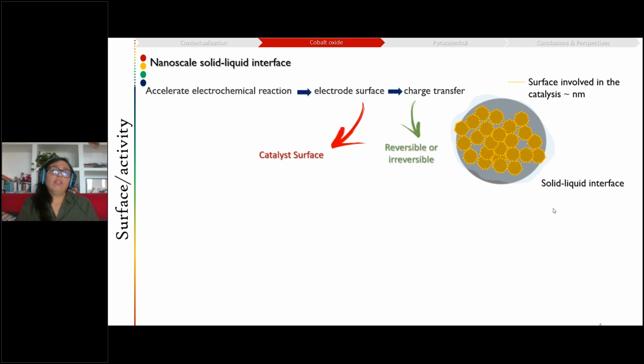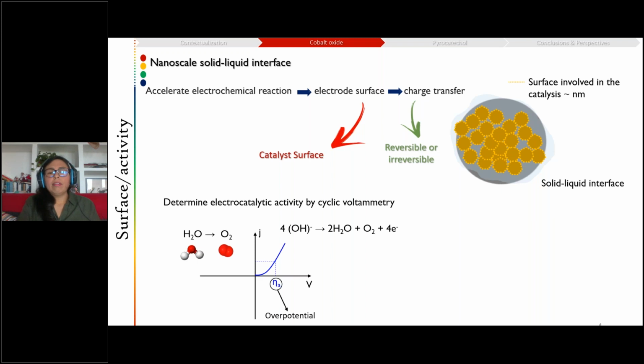So this is where the TEM has an important role, of course. And what we want to see is what happens at potentials that are relevant for our reaction, meaning that we want to decrease the overpotential that is applied to drive the reaction. We typically do this by cyclic voltammetry, for example. We are able to observe how the current changes with an applied potential, and we want to minimize the amount of potential that we need to apply.